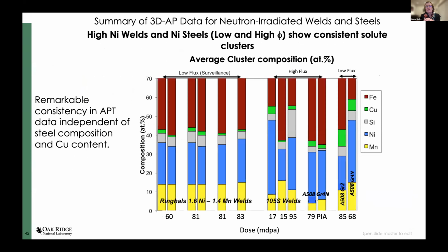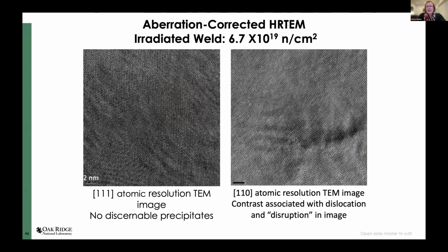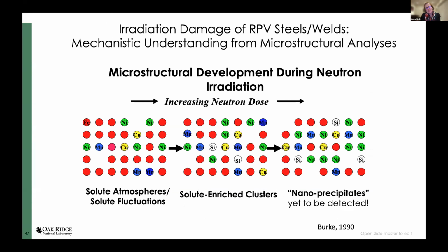And this is just looking at consistency of data from various irradiation conditions, various compositions, to get an idea of the fact that there are very specific elements associated with this. Now, for those of you that do atomic resolution imaging, this is some aberration corrected TEM, but it wasn't possible to pick up any type of precipitate feature, even though we were complicated at some points by oxide. So this is technically what we've got, and we're still hoping to get to the nanoprecipitate side.